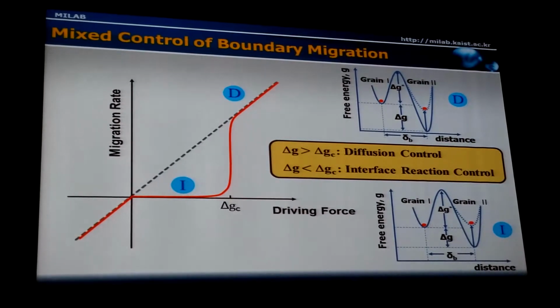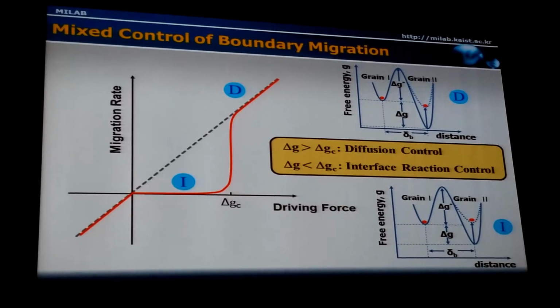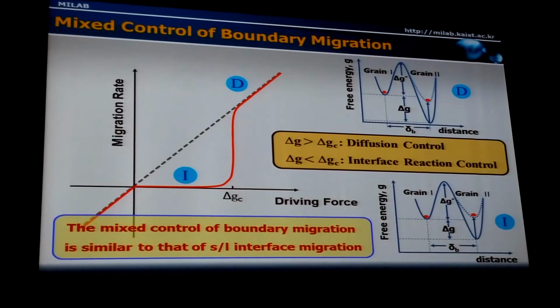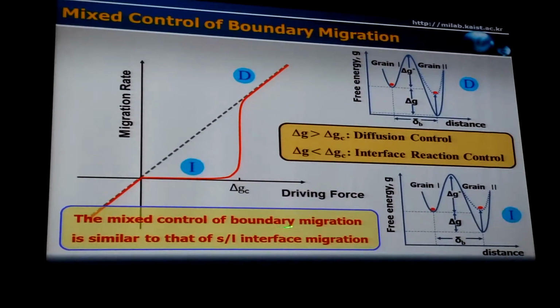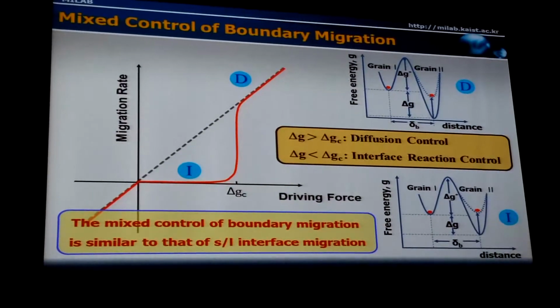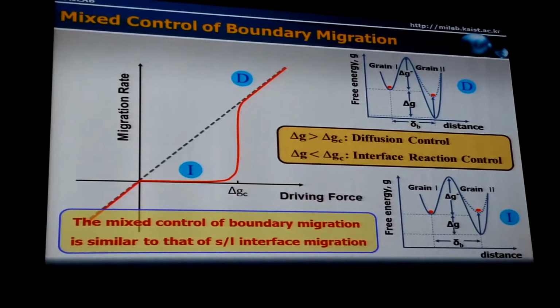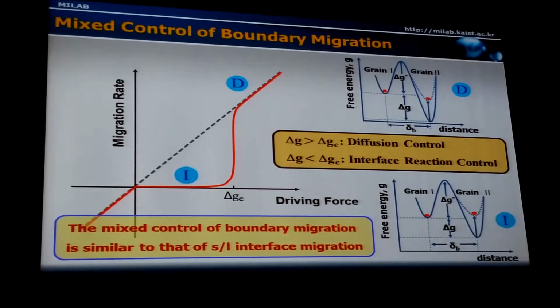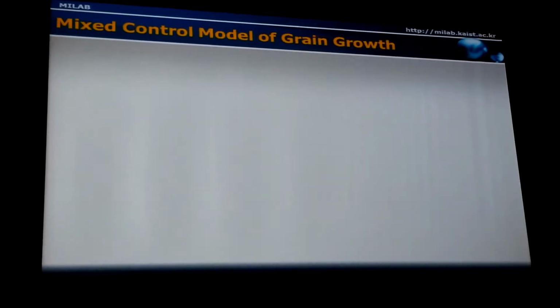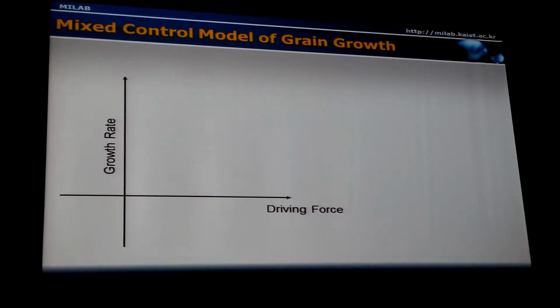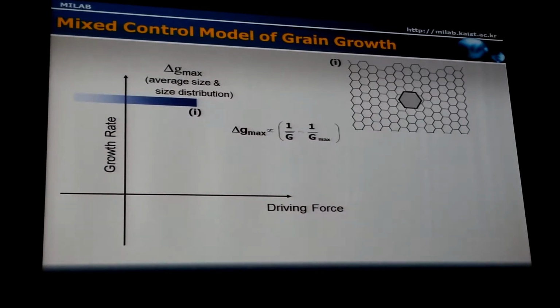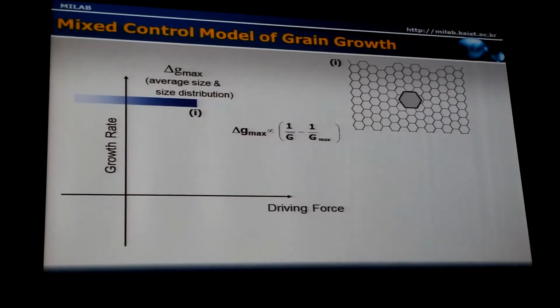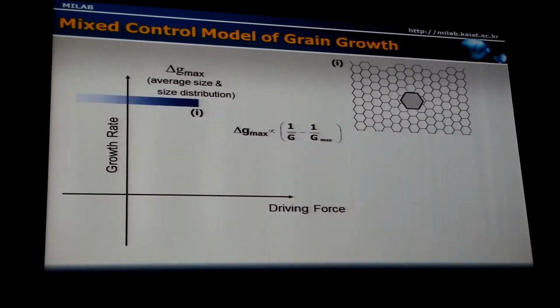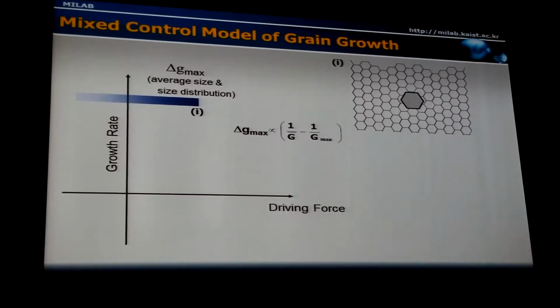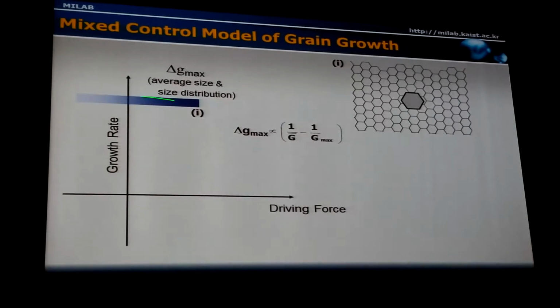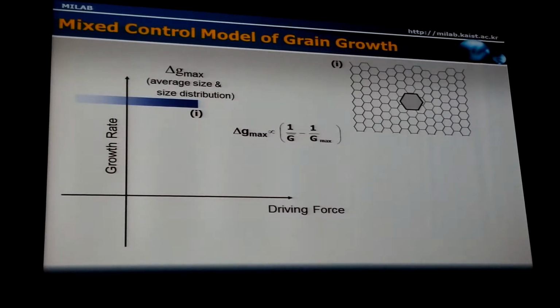Now, let's consider a growth of many grains and shrinkage of many grains. And this mixed control of boundary migration is similar to the mixed control of solid-liquid interface. So we can apply this idea to the migration of the solid-liquid interface and grain boundary as well. And from this, we can deduce the mixed control model of grain growth. Consider we have a numerous number of grains, and each grain has its own driving force for growth or dissolution. So the largest grain will have the maximum driving force for the growth, and the smallest grain will have the maximum driving force for the dissolution.